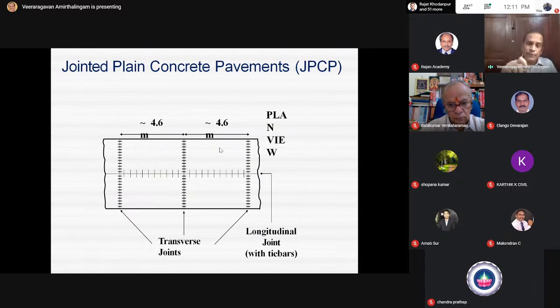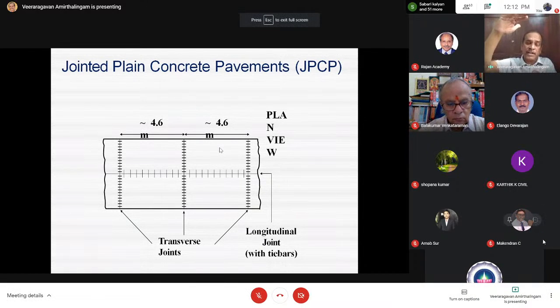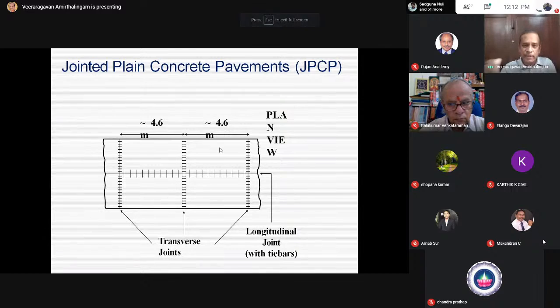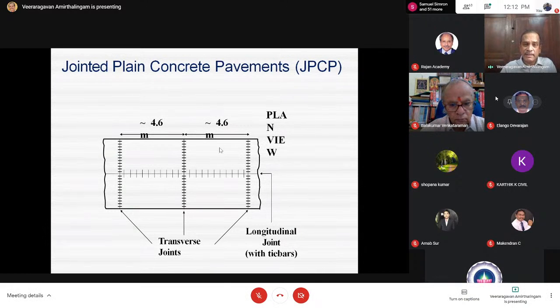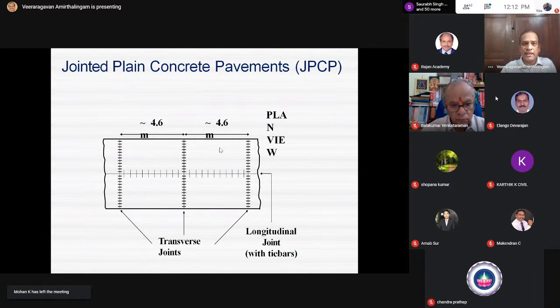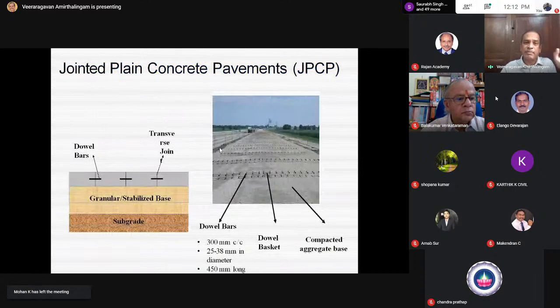But thickness is reduced while increasing the width. By increasing the width, you are adding more joints because the longitudinal joints should continue. So one has to work out the cost economics of a 35 centimeter thick concrete pavement, 7 meters wide, vis-a-vis a 2.7-meter wide pavement with a paved shoulder, and which is economical with two joints or three joints. That has to be worked out. Performance is different; performance has to be predicted.